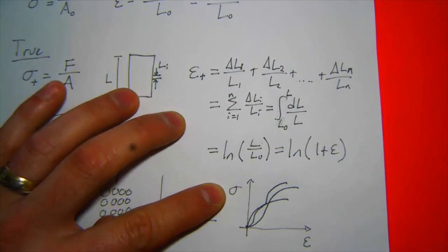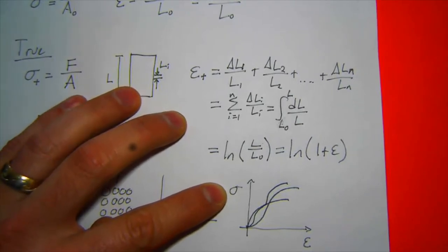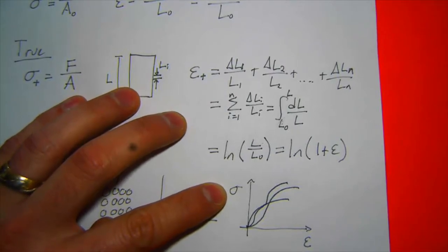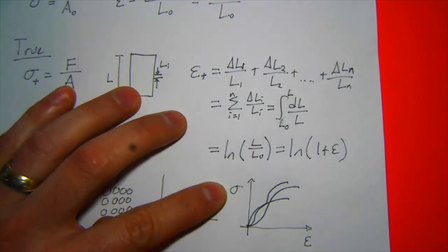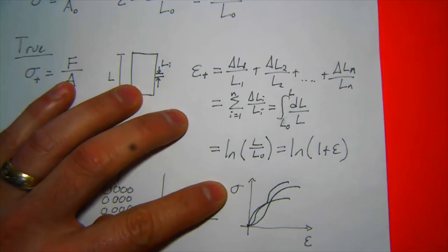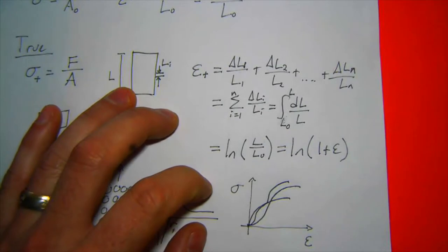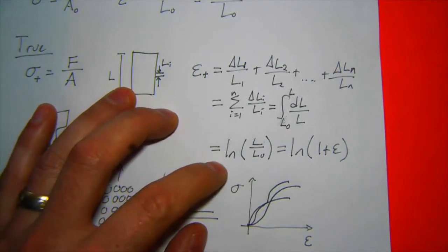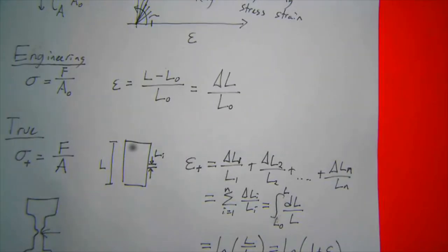Yes. How accurate is the elastic assumption if you have an infinite cycle life for something that you can do over and over again, like with a polymer or something like that? So the closest thing to a perfectly elastic behavior is actually a glassy material, either glass or metallic glass, because there are very few plasticity or deformation mechanisms, and they also correspondingly have very high fatigue cycle life, interestingly. But yeah, that's a rare exception. So there are materials that are almost elastic.